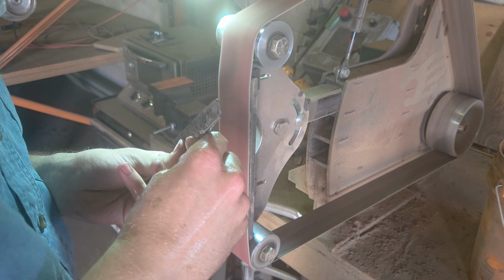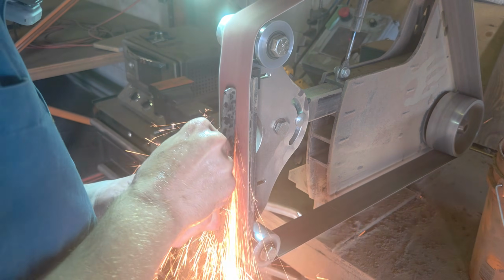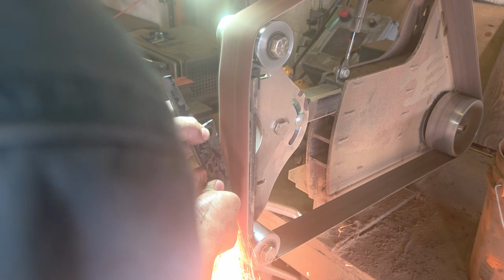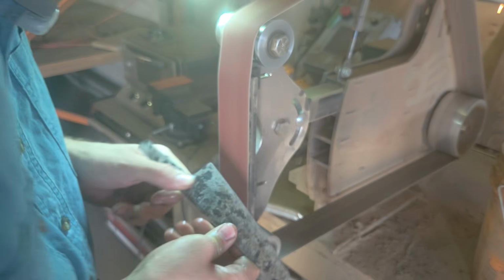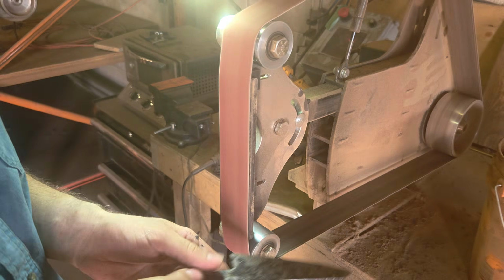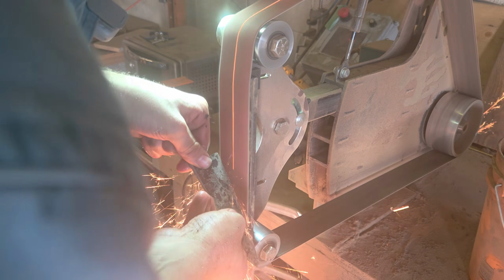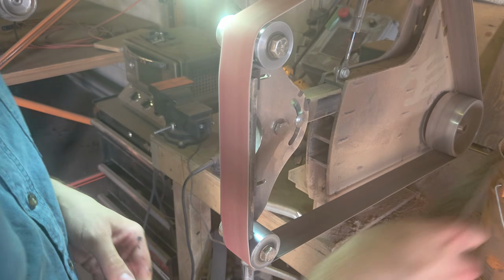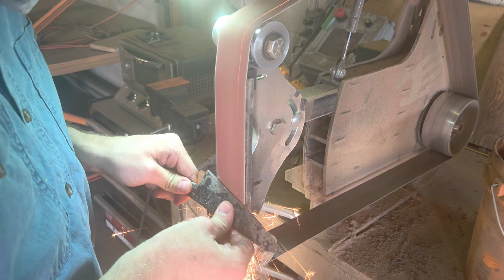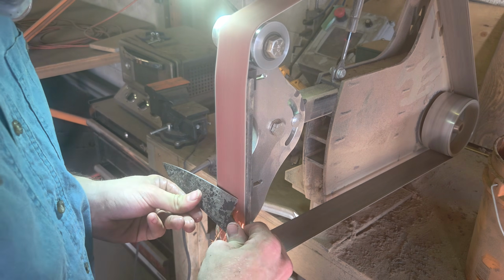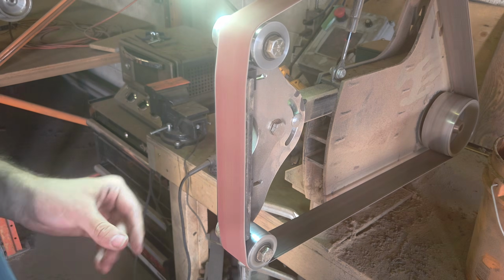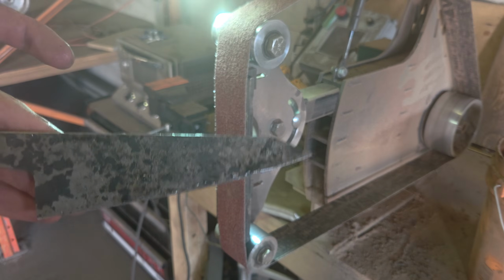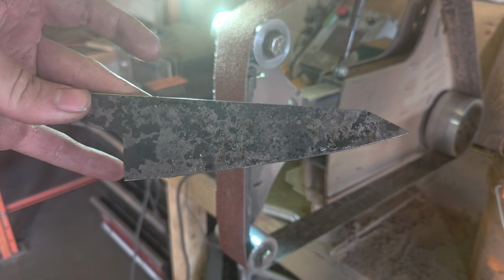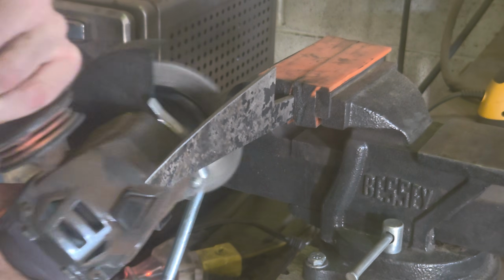a factor of time and the temperature we reach, and the temperature is a lot more important. So I think as long as the blade has fully reached that temperature through the entire blade, then the temper should be fine as long as it holds that for at least a little bit, because temperature is more important than the time. And I could be wrong, but I believe most of these tempering recommendations are for more industrial applications, which are a lot bigger pieces of steel, so it takes a lot of time to make sure that piece fully reaches that proper temperature. But for a blade like this, it can reach the temperature in the oven very quickly.